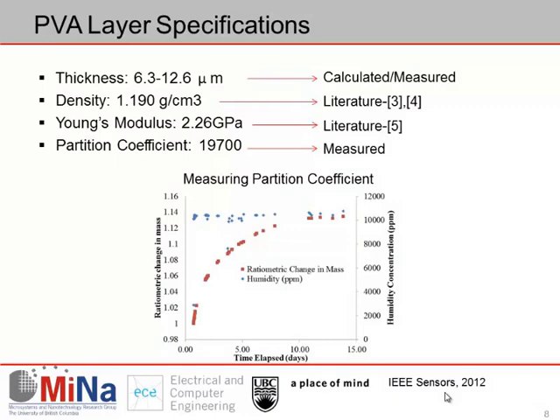We then were able to compare these results with a few results obtained otherwise in other methods, so either by measurement or through literature. We couldn't find something that would be able to address tension, but we were able to compare with different values of thickness, density, Young's modulus, partition coefficient.